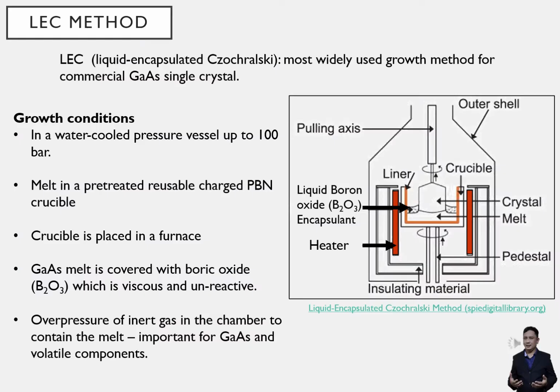LEC is the most widely used growth method for commercial gallium arsenide single crystal. Growth takes place in a water-cooled pressure vessel for pressure up to about 100 bar. It houses a pretreated reusable charged pyrolytic boron nitride crucible that is surrounded by a furnace including heat insulation. The gallium arsenide melt is covered with boric oxide, which is viscous and unreactive. This allows an overpressure of inert gas to be applied so as to contain the melt, which is important for gallium arsenide and its volatile components.